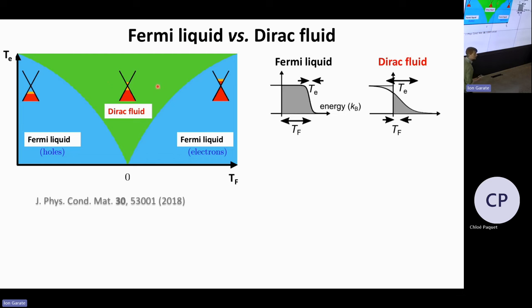And the best way to understand what that entails is by looking at the Fermi-Dirac distribution in the two cases. So in the case of the Fermi liquid, you actually have a quite large Fermi energy, so you only have electrons in the conduction band or only holes in the valence band. Now, in the Dirac fluid case, on the right, you have quite a lot of broadening because you have a large electron temperature. And your Fermi energy or temperature is quite small, so you're close to the Dirac point. So what you then have is a simultaneous presence of holes in the valence band and electrons in the conduction band. And this gives rise to novel phenomena in this regime.